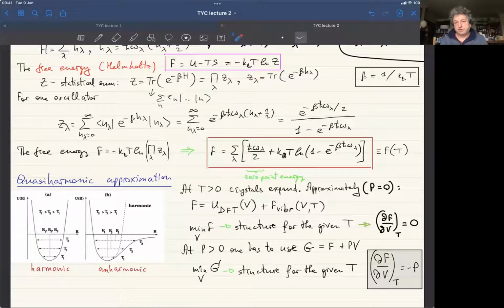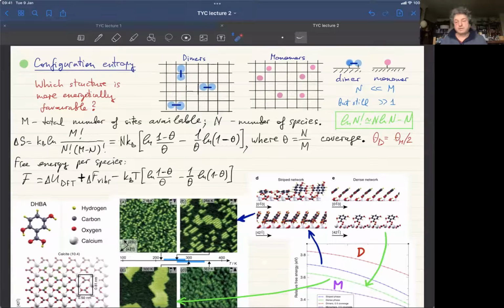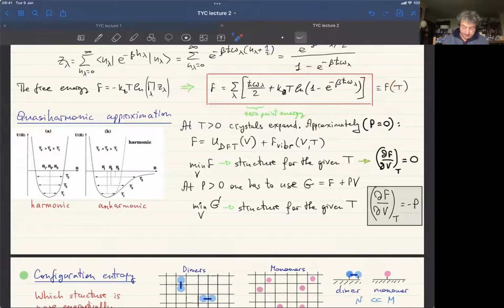For a general crystal structure, this is not that straightforward. A crystal structure is specified generally, for a very general unit cell, by 6 parameters: a, b, c, the sizes of the primitive cell, and angles alpha, beta, gamma between the primitive translations. And then it's very difficult to perform this calculation in practice. You have too many parameters. So you have to build a dependence of the free energy with respect to all these 6 parameters. And then for all values of those parameters, you have to calculate the vibrations, which becomes very, very difficult to do. But before we go into this, let me show you some other quantities where that so-called quasi-harmonic approximation, which is basically a way of using this free energy in some calculation, can be of use.